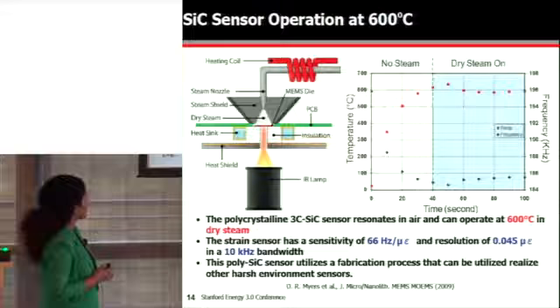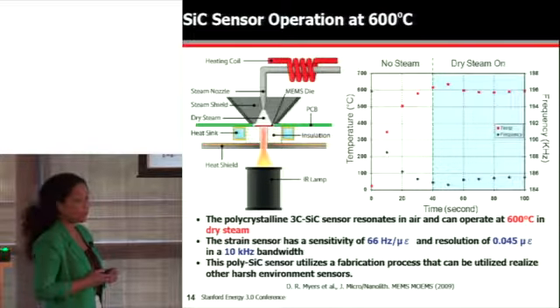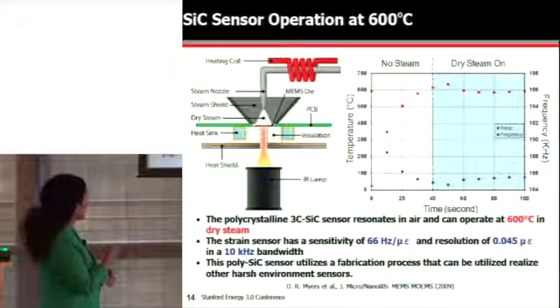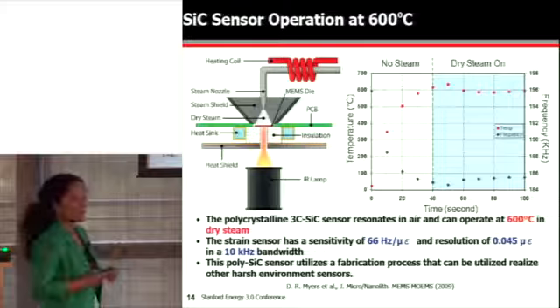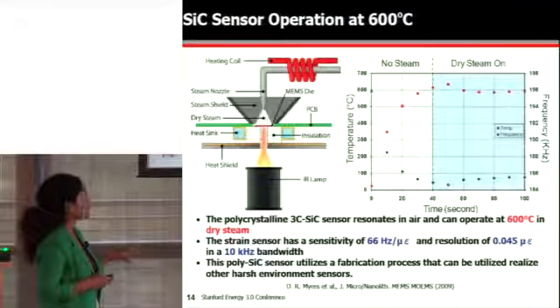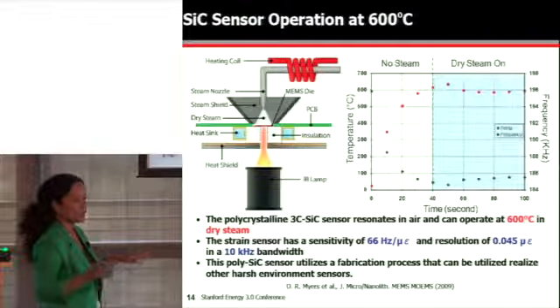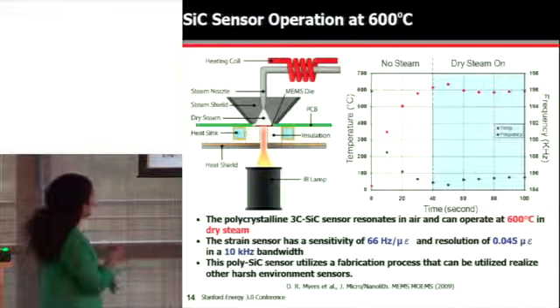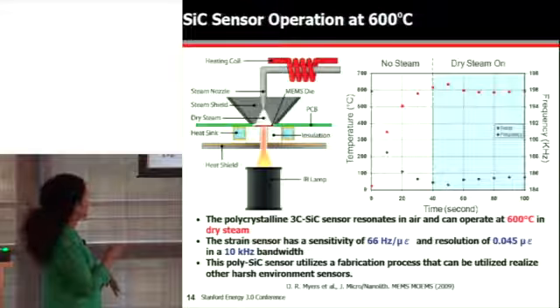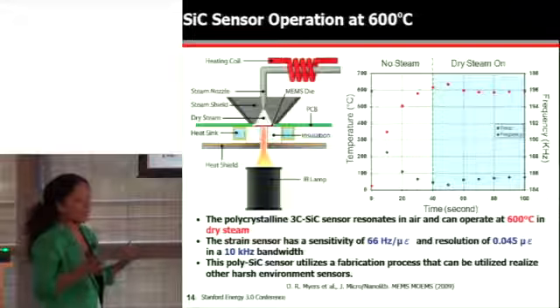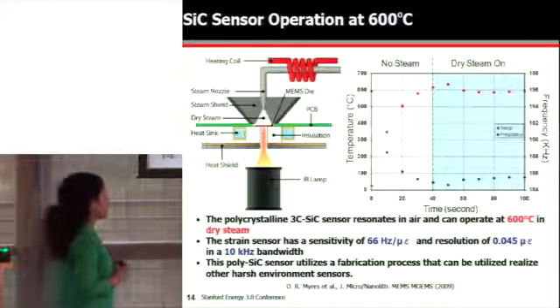This device was tested at 600 degrees C using an IR lamp, so locally heating the backside of the chip. At this point of the project, we didn't have the electronics. We were developing them in parallel. So the interface electronics were polymer using PCB, so low temperature. But we were able to locally heat the actual sensing device using an IR lamp, and then also exposing the unpackaged sensing device to a very hot oxidizing environment, dry steam.